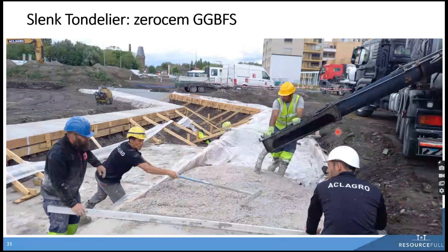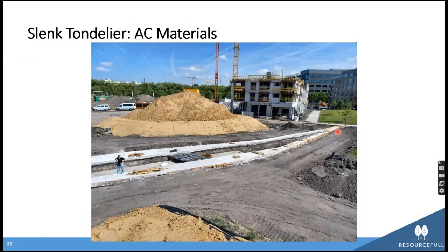We put some footpaths in Ghent, where we made a clinker-free geopolymer, but 50% of the sand and 100% of the gravel was replaced with recycled concrete sand and recycled concrete stones. Also what Niki showed before, and he is right. When you use recycled concrete stones, it doesn't change the MKI score of your concrete. But if you can combine it with a geopolymer, maybe we have a bit even the best of both worlds. And here is my wife inspecting the concrete quality. She was not as impressed as I hoped.